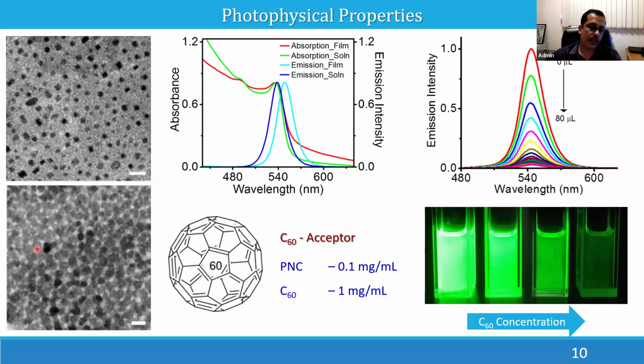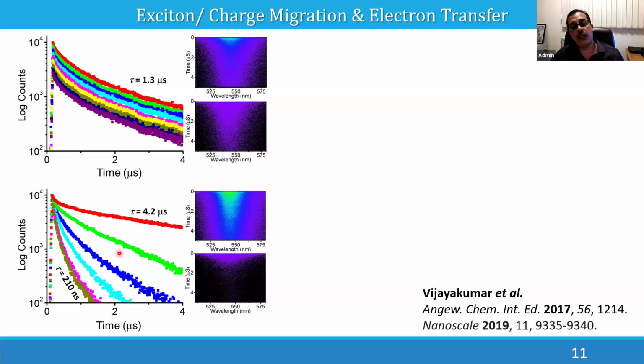And this is in solution, but in film, you can see the nanocrystals are very close to each other. And in this film state, once you excite at one point here, that exciton can travel to other regions. Okay, in solution, it is not possible because these are isolated nanocrystals. There is no connectivity between neighboring nanocrystals. But in the film state, the nanocrystals are well connected. They are close to each other. So when you excite at one point, that exciton can easily transport to the other part of the film. That is called the excitation energy migration. The exciton is migrating. Okay, that energy is migrating from one point to another point, and finally it reaches the acceptor.